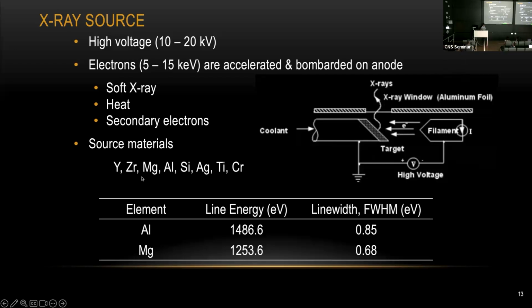In the old days, people tried all different kinds of materials for XPS measurement. But nowadays, in most modern XPS machines, people just use aluminum or magnesium. These two materials have been chosen simply because they have much narrower line widths, so they can give you better resolution. But for aluminum, you can put more power to the metal, so that's why most people nowadays just use aluminum. Occasionally, you might find a machine using magnesium, simply because they want a little bit higher resolution. You can see the line width for magnesium is actually a little bit lower than aluminum. But again, aluminum has much higher power, so you can penetrate a little bit deeper into your surface compared to magnesium.